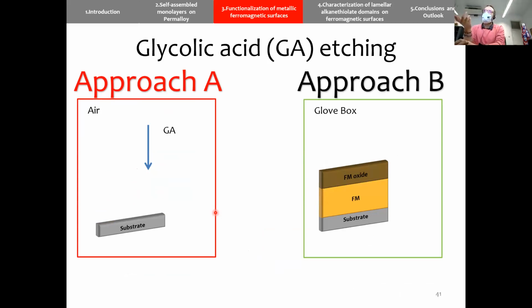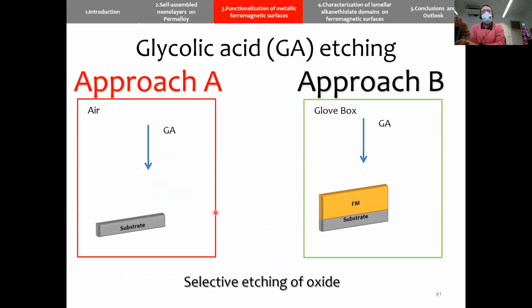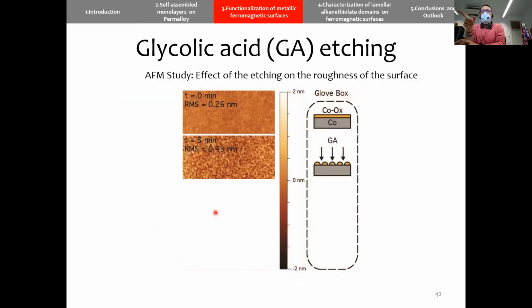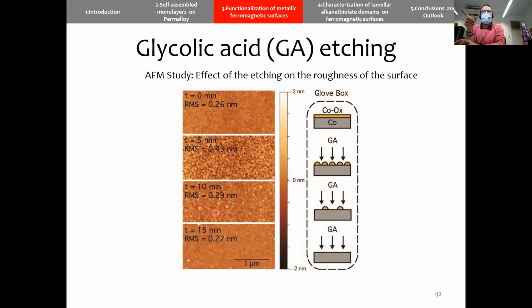In approach B, in the glove box, we observe that, yes, the glycolic acid will attack the oxide, but since there is no more oxygen, we will not observe reoxidation, and so the glycolic acid is not touching the ferromagnet. And in this case, we have a selective etching of the oxide. And also the roughness is maintained. We can see a clear surface after barely 15 minutes of exposure.